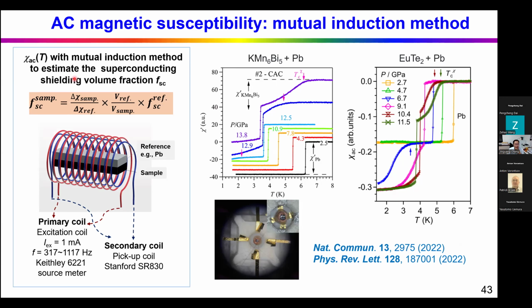Here we use the AC magnetic susceptibility to estimate the superconducting volume fraction. It's very simple. We make two coils, and we put the sample and a reference in these coils. When the sample becomes superconducting, the repulsion of the magnetic flux will produce a drop in the magnetic susceptibility. By comparing the drop between the reference and the sample, we can estimate the superconducting volume fraction. For example, here we measure this sample, and we put the sample and a lead in a coil. So this is the transition from the lead.